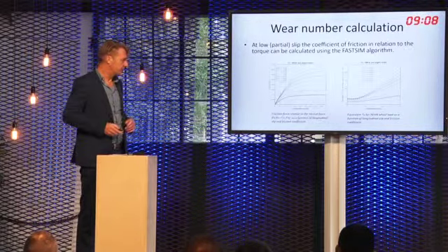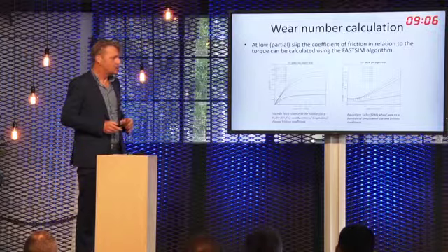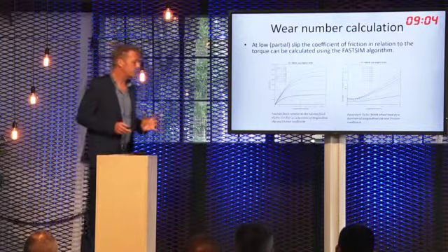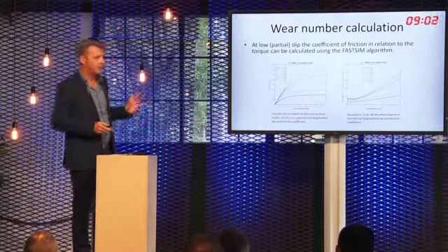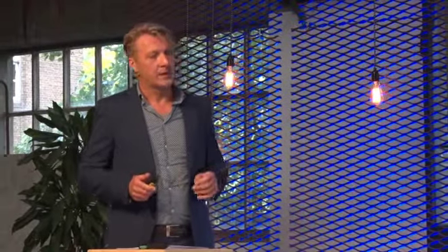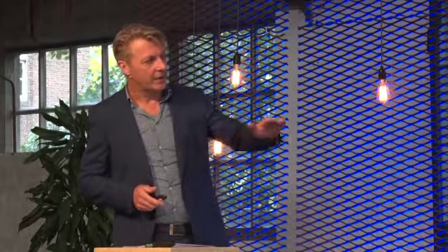So setting up the test, from the set longitudinal slip and the measured torque and the measured normal force, we could then understand what the operational friction coefficient is, and from this operational friction coefficient, together with the normal force and the disk curvature and the set slip levels, we can go to the T gamma level we want to test.